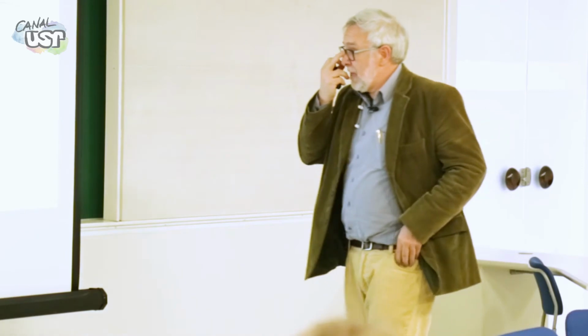What happens here is you heat very fast, so water is released from the gypsum, the hydrated water, into the atmosphere. Instead of going to the vent, you create a water vapor atmosphere. It's like a pressure pan. And this water vapor atmosphere moves the second peak a little bit farther away, okay? So if you do that, you can clearly separate the amount of hemihydrate and anhydrite.